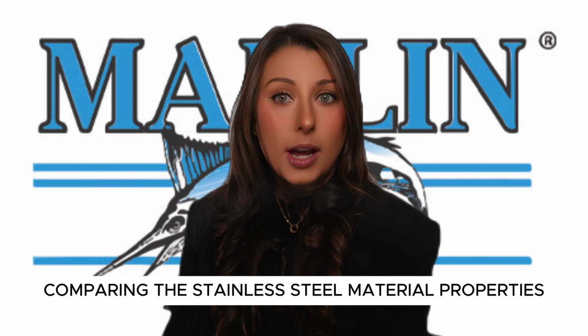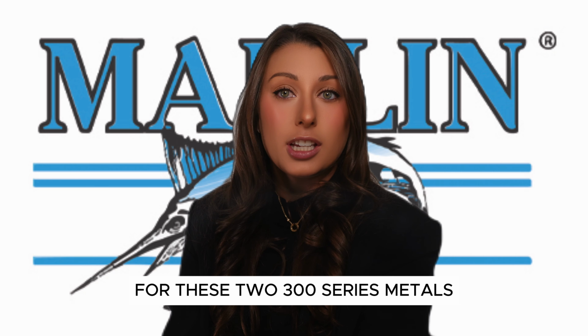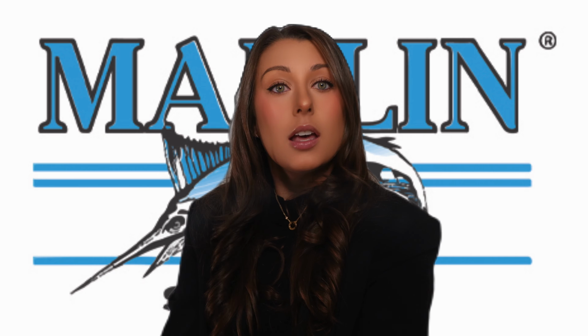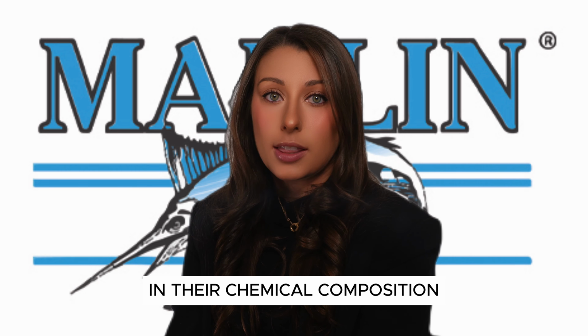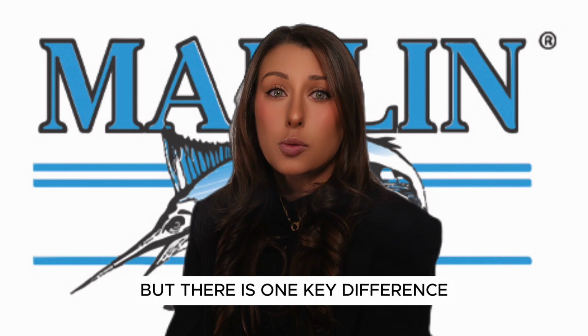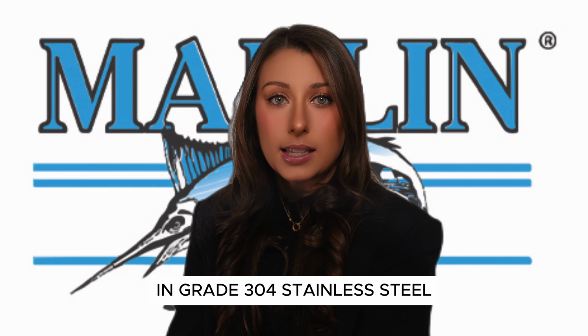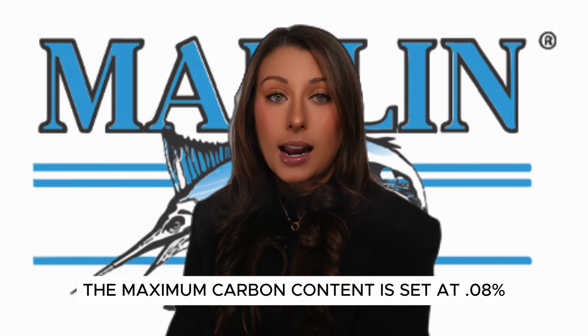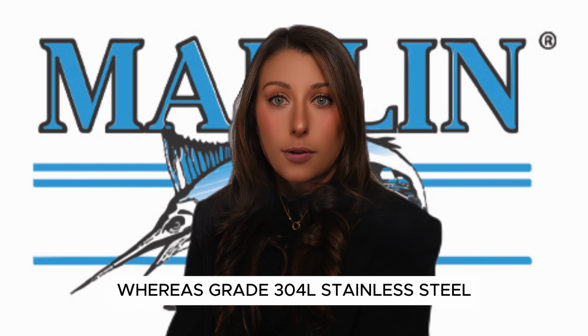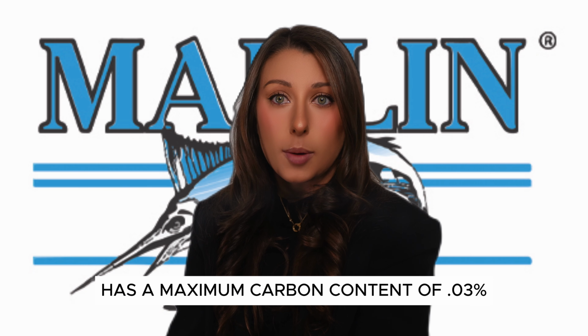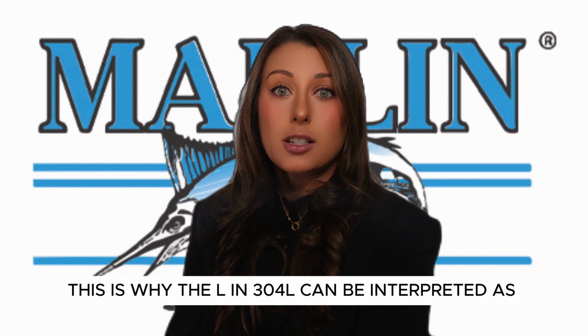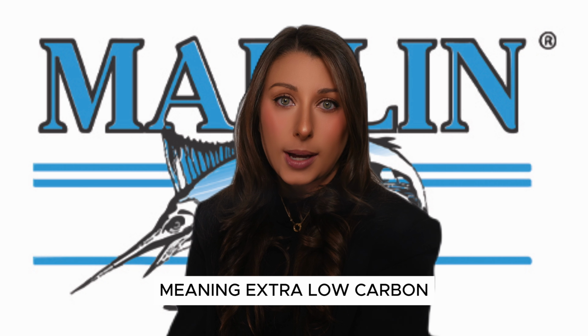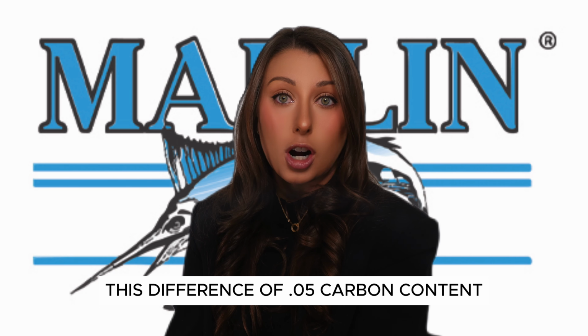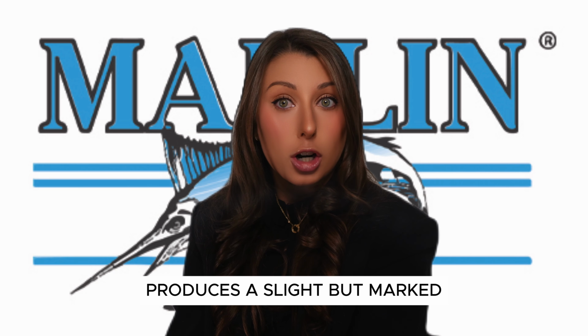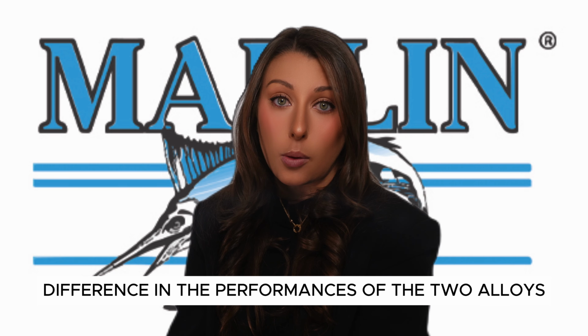Here's a quick table comparing the stainless steel material properties for these two 300 series metals. These two alloys are remarkably similar in their chemical composition, but there is one key difference. In grade 304 stainless steel, the maximum carbon content is set at 0.08%, whereas grade 304L stainless steel has a maximum carbon content of 0.03%. This is why the L in 304L can be interpreted as meaning extra low carbon. This difference of 0.05 carbon content produces a slight but marked difference in the performances of the two alloys' stainless